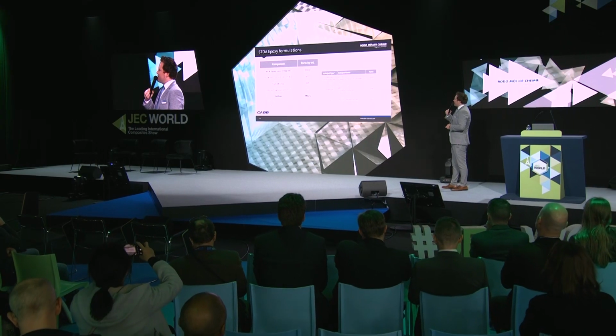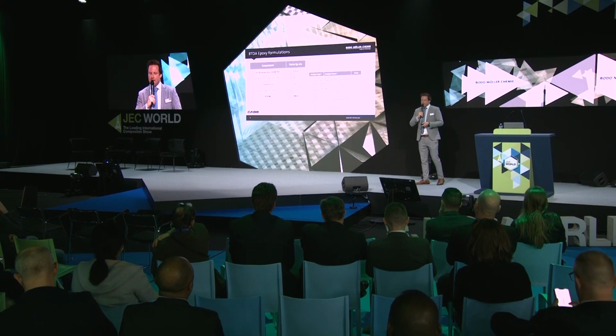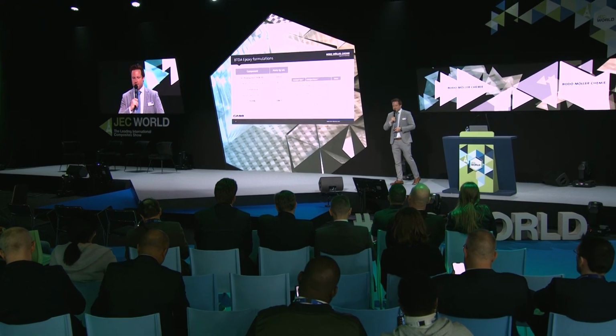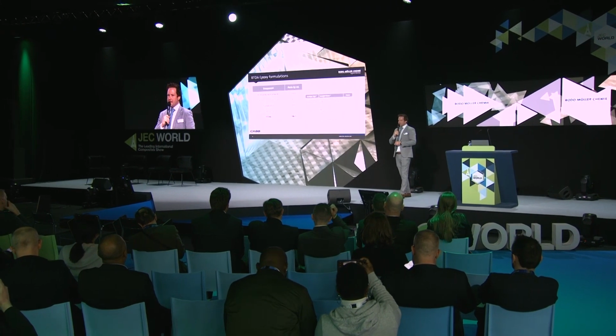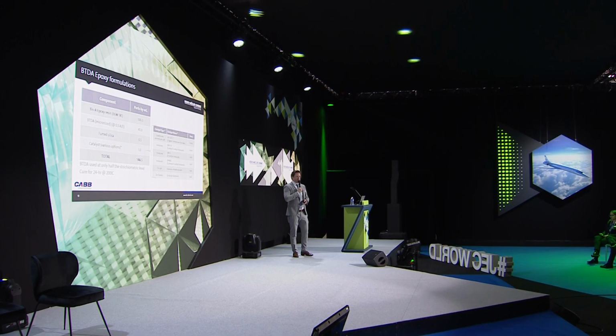Here I would like to provide even more detailed information on how to process BTDA formulations. In a very simple epoxy formulation, we need of course the bisphenol A based resin. We use the BTDA dianhydride curing agent. You can add some fumed silica if you want to play around, for example, with the viscosity. It's not necessary, but you can also use catalysts. The catalysts can reduce the curing temperature, but also the curing time. There are different kinds of catalysts that can be used within this chemistry: some kind of ammonium salts, but also different imidazole derivatives are great solutions here.